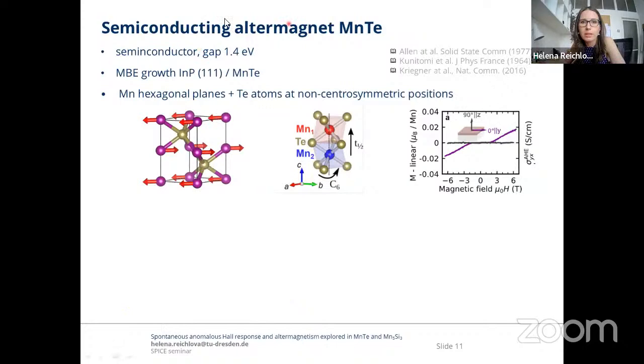Manganese telluride is a well-known material. It's a semiconductor with a gap of 1.4 electron volts. And our samples were grown by Günther Springholz on indium phosphide, MBE grown. And manganese telluride has these manganese hexagonal planes and the tellurium atoms in non-centrosymmetric positions. And this is the conventional way to look at the unit cell.